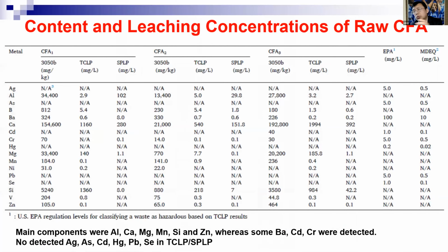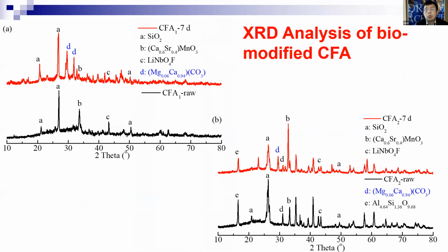So now I've finished the steel slags. Now I move to the coal ash. For coal ash, we also tested using these methods to see what kind of original metals are in there. We see the main components are aluminum, calcium, magnesium, and manganese in the original. But when we modified the coal ash by mixing it with bacteria, the XRD shows new carbonates here.